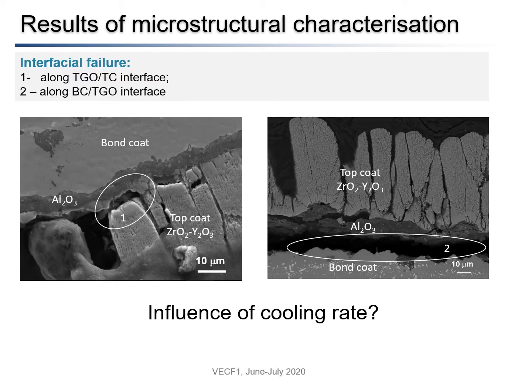It was shown that for different samples the problem arises for both interfaces, along the thermally grown oxide-TC interface and along the thermally grown oxide-BC interface. First of all, the investigation of cooling rate effect was carried out.